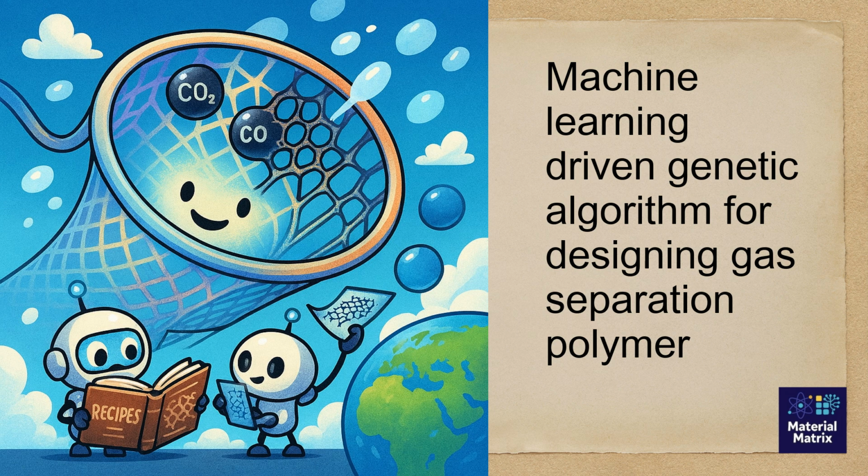So these methods expedite the design process by efficiently analyzing complex data and intelligently generating new polymer combinations. The application of random forest regression and ECFP fingerprinting, for instance, has proven highly effective in predicting gas permeability and selectivity. The exciting news is that this approach has already yielded significant results, with the genetic algorithm identifying over 20 novel polymer membranes that surpass existing performance benchmarks for CO2/N2 and CO2/CH4 separation. So these new polymers exhibit promising traits, including high glass transition temperatures and specific functionalities that enhance CO2 interaction, indicating their strong potential for practical applications.